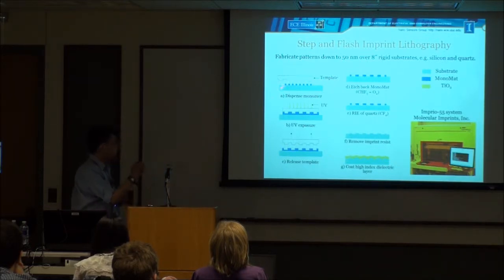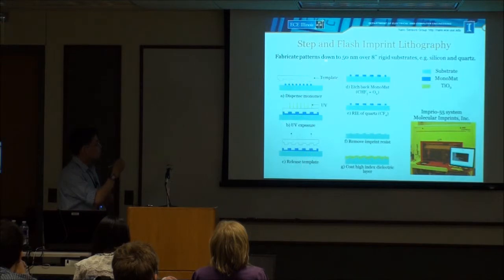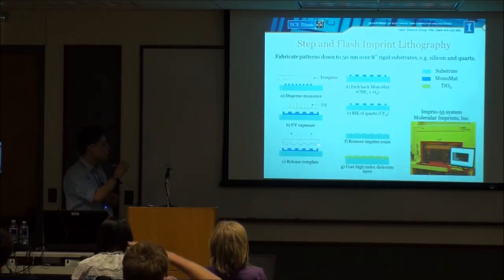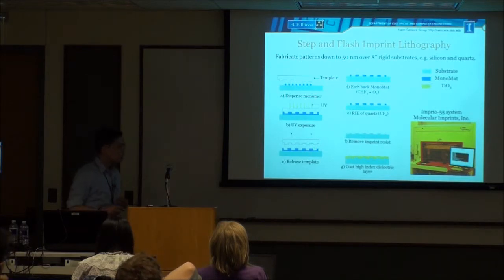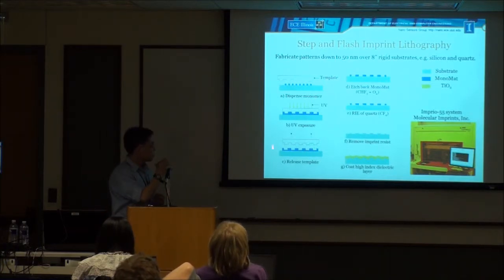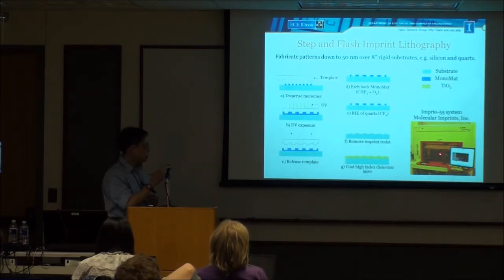The first few steps of step-and-flash imprint lithography are the same as replica molding. We start from a template and squeeze UV cure polymer between the template and substrate, then apply the template onto the substrate and squeeze the UV cure polymer material. After UV curing, the template is removed from the substrate. Those steps are similar to nano replica molding, but after that, since this method is very controllable, it allows us to control the uniformity of this imprint layer.